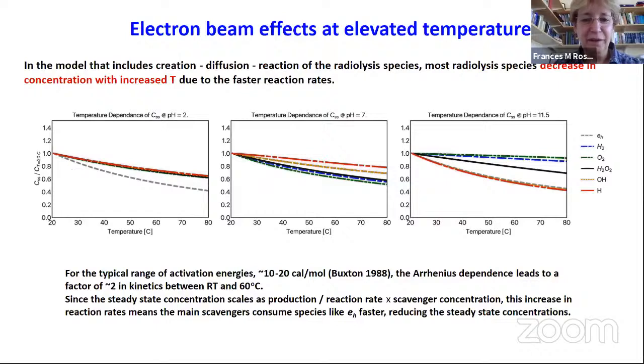Okay. And of course, temperature changes everything. One thing it changes is radiolysis. Most radiolysis species actually become less concentrated because the reaction rates are faster, and so this tends to mean they get consumed faster and therefore have a lower steady state concentration. So I'm not saying this is a good way of reducing the effects of the electron beam on the electrolyte, but it is interesting to consider that the radiolysis effects are lower at high temperature.